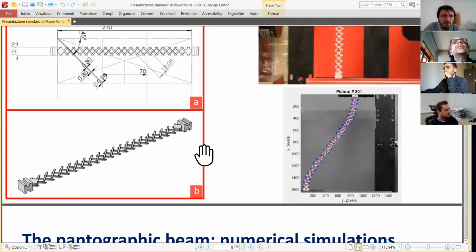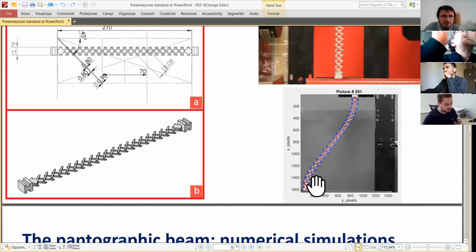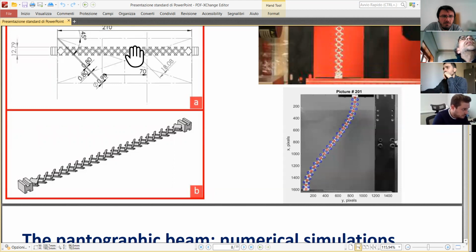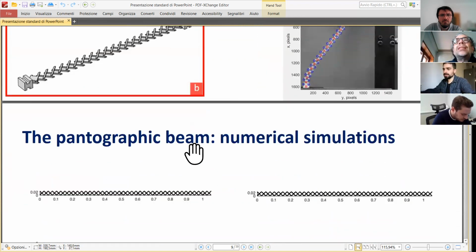However, I can tell you with words what happens. This beam behaves in a range of displacements like a beam. When you reach a threshold, it becomes a cable. So you have a kind of phase transition. When these two beams here, constituting the typical element of our structure, become parallel, then it becomes like a cable, because here you have pivots which are perfect at the top and at the bottom. So you have small segments which are articulated like a catenary in a sense. So this metamaterial has a mechanical phase transition inside.